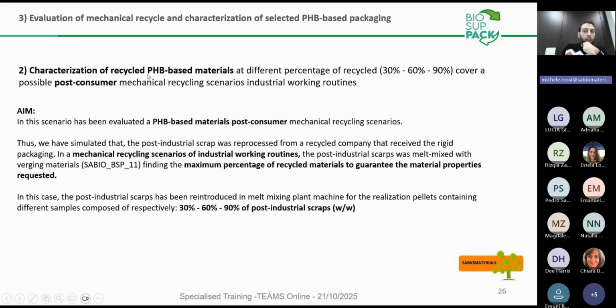The second example of material recycle is to obtain different grades of material that contain 30, 60, and 90% of recycled material. In this case, we are analyzing a scenario of post-consumer, so a waste manager, as I said before, manages this, and the material will be scrapped and reintroduced in a formulation at different percentages. So in that case, we introduced different percentages of post-industrial scrap, after milling internally, with virgin material, essentially Sabio BSP 11.